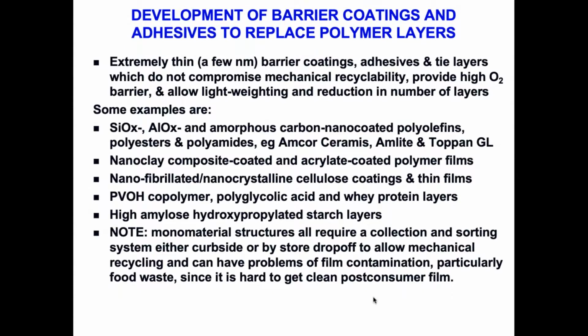nanoclays and acrylate coatings, nanofibrillated and nanocrystalline cellulosics, and then a different group of materials which still allow recycling because during the washing process in the recycling, they either hydrolyze or dissolve and disappear in the sewer system, where they are biodegraded. So these would be things like polyvinyl alcohol, polyglycolic acid, whey proteins, and hydroxypropylated starch.